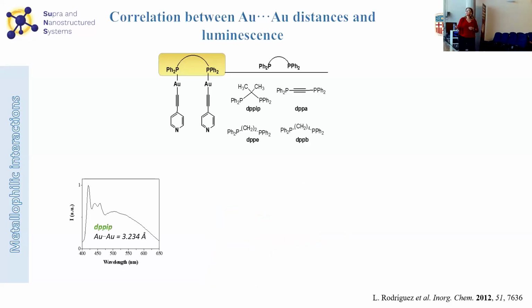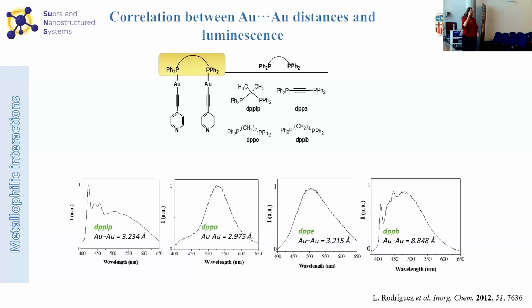So these two bands can be in different proportions, or even hindered one below the other, but they are present in all cases. We can see that we can be close to 3 angstroms, but also at 8 or near 9 angstroms, these two bands are present.